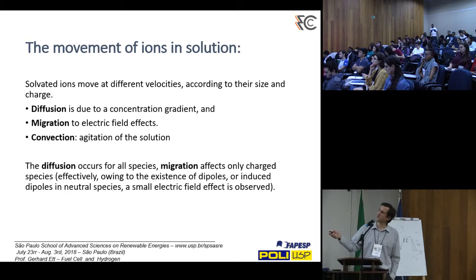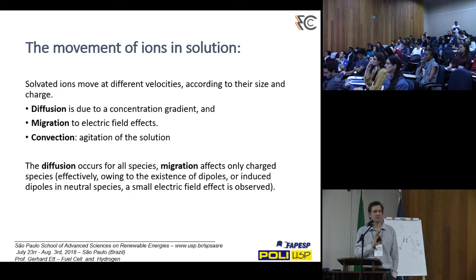The convection is the agitation of the solution. The convection could be due to the difference of temperatures. In surface finishing plating, in chromium electrodeposition, there is a difference of temperatures. Then you have a convection of the solution. Then this convection of the solution will increase the diffusion. Okay. The diffusion occurs for all species. Migration affects only charged species. This is the important point.